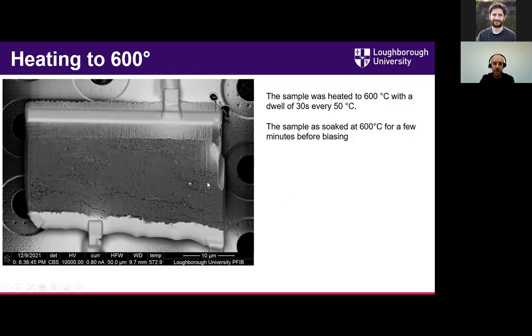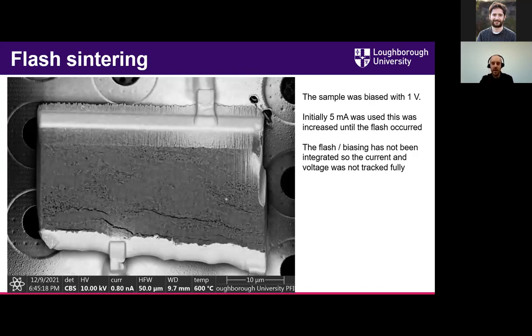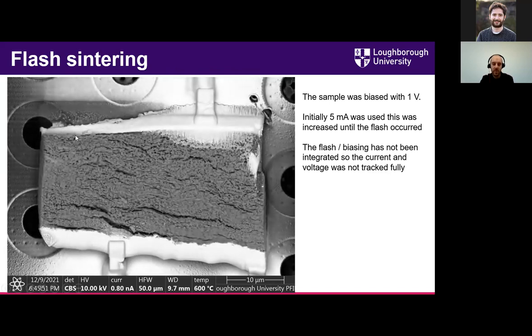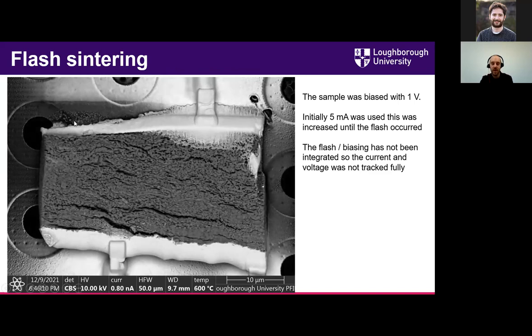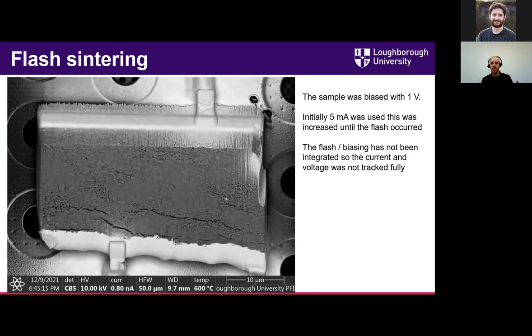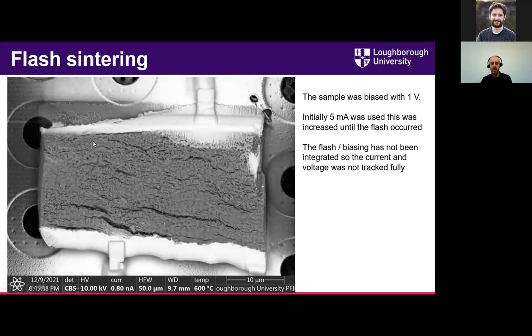So this is what the sample looks like just being heated up to 600 degrees. You can see there's not a lot of change. Not much has happened, maybe just the cracks have changed slightly. And then what we're going to do is apply the voltage, and you can see that as the voltage is applied, the whole sample comes together. Some cracks start to form. We lose this top edge over the top left-hand side,